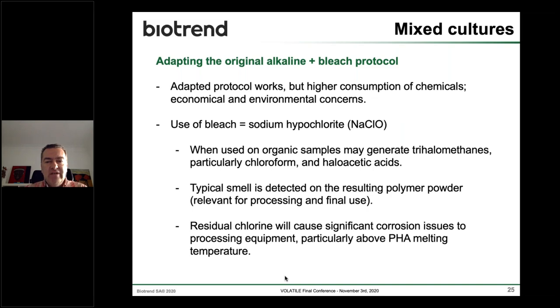and this is a strong indication that we may have a generation of organochlorinated molecules, which are hazardous, extremely hazardous, and also the generation, with the residual moisture, of hydrochloric acid vapors that would completely corrode the equipment of the processors.